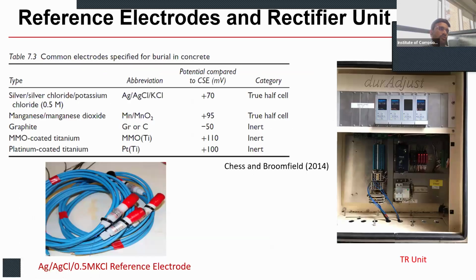In monitoring, we use embeddable reference electrodes for concrete. These reference electrodes are generally of two types. One is the true half cell potential electrodes, which for concrete environment are generally silver chloride electrodes or manganese dioxide electrodes. Other than that, we have some decay probes, the pseudo reference electrodes or inert probes as we call them. These decay probes are inert electrodes like graphite, MMO-coated titanium, or platinized-coated titanium, and cannot measure potential values.